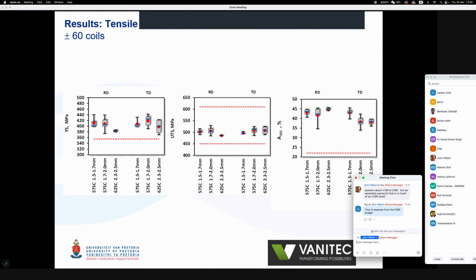So what we did was, initially we did a 150-ton trial. That's just a handful of coils. But after the success of the 2.5 millimeter material, we decided to go thinner, and we did a 1,000-ton trial, plus minus 60 coils. And here we have some tensile results for you.